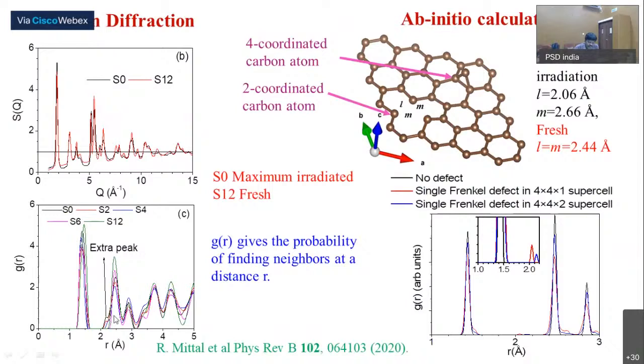2.2 angstrom. We have interpreted this data using ab initio calculation, and we can see that this is the interstitial atom. These are the various distances. If one atom is knocked out from here and goes here, then this distance is reduced to 2.06 and this is increased to 2.66. But in the fresh sample, these L and M are the same, and equal to 2.44. So the peak at this position is due to this new bond of 2.1 angstrom. We have also shown from our ab initio calculation that this additional peak at about 2.1 angstrom appears when we create one Frenkel defect in a supercell of 4x4x1 and 4x4x2.